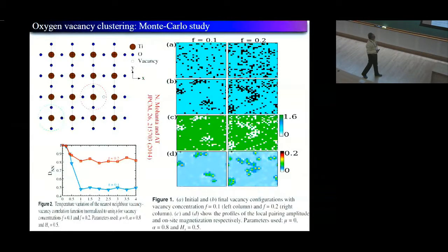We did a Monte-Carlo calculation, and particularly we were bothered by the issue that people reported vacancy ordering, and vacancies form patches. But then what we found is that each of these vacancies, for example, has a charge of -2. So given that, you just do the calculation, and what you find is that at sufficient disorder, the disorder pins the vacancies, these oxygen vacancies, and they sort of cluster around. And this is simple energetics that gives you that.